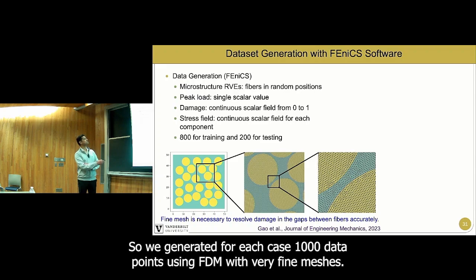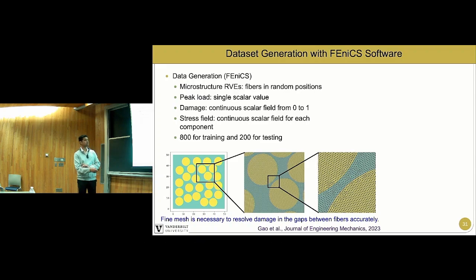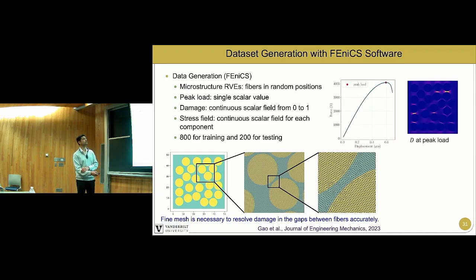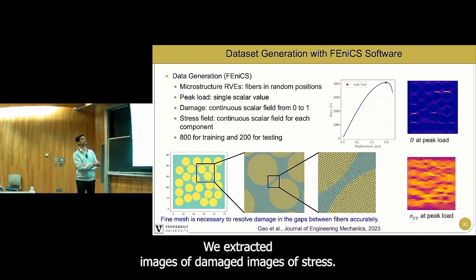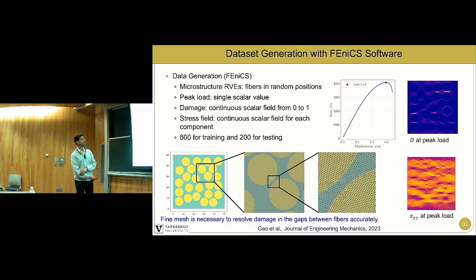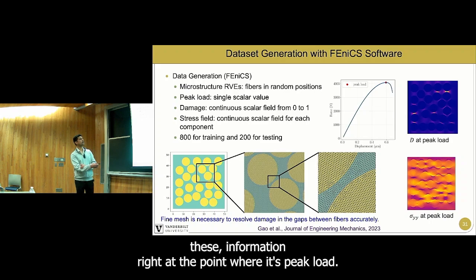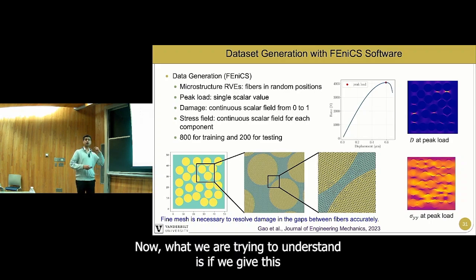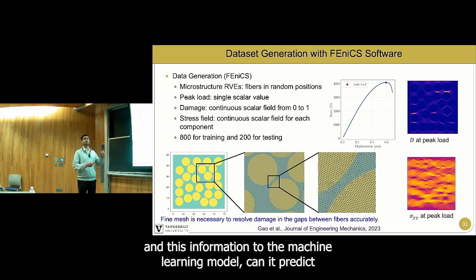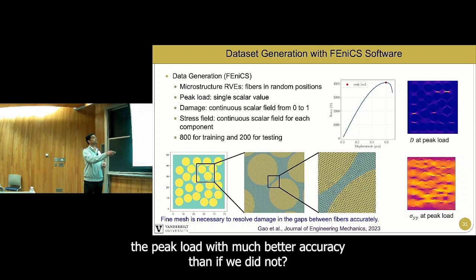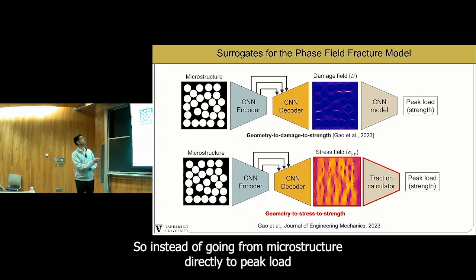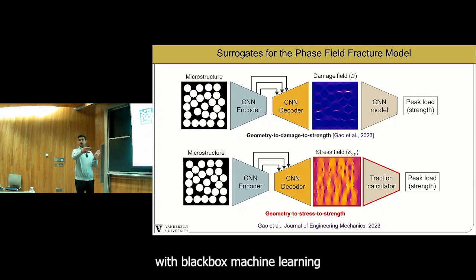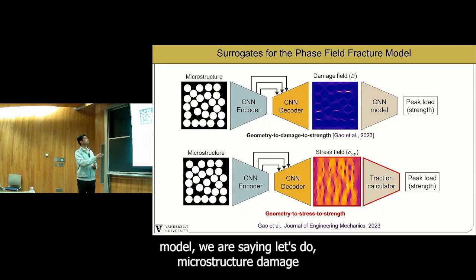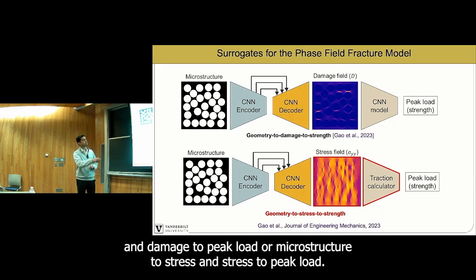So we generated for each case 1,000 data points using FEM with very fine meshes. We used our Phoenix adaptive codes for it. We extracted peak loads. We extracted images of damage, images of stress. And you get this information right at the point where it's peak load. Now what we are trying to understand is, if we gave this information to the machine learning model, can it predict the peak load with much better accuracy than if it did not, right? So instead of going from microstructure directly to peak load with a black box machine learning model, we are saying let's do microstructure to damage and damage to peak load, or microstructure to stress and stress to peak load.